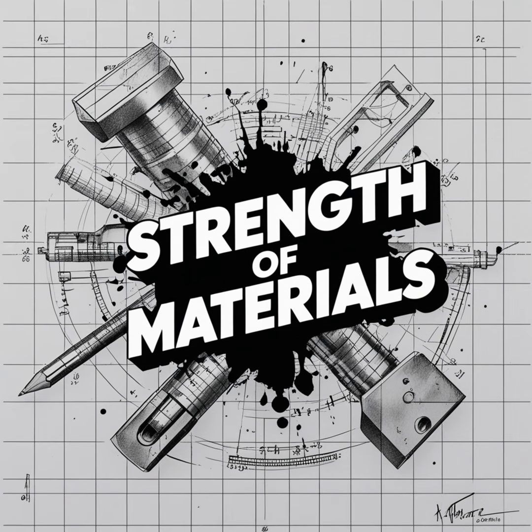And what does a perfectly flat horizontal line actually mean for the physical metal? It means that if you keep the applied cyclic stress strictly below that specific endurance limit, the component has an effectively infinite life. Infinite life, literally forever. From a fatigue standpoint, yes. The micro damage that is created during the loading cycle is so minuscule that it is entirely arrested by the material's internal microscopic barriers, the grain boundaries.